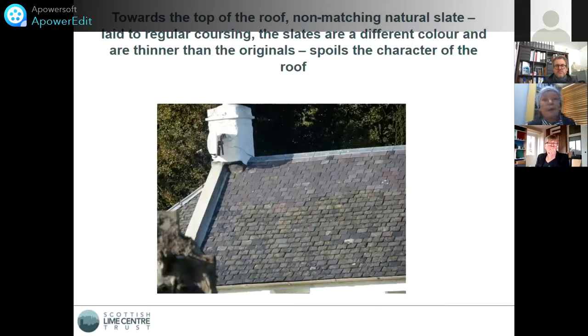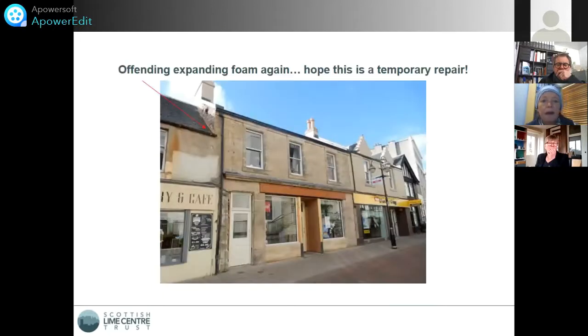If we have a look at the top of this roof, you can see it's a natural slate roof, but the repair at the top of the roof has been made with a non-matching natural slate. In this case, it's probably a Welsh slate, laid to very regular courses, and the different colour and the thickness of the slates are different from the originals, and it spoils the character of the roof, which was much thicker slates laid in random diminishing courses. And here we see the offending expanding foam again, and I do hope this is a temporary repair.